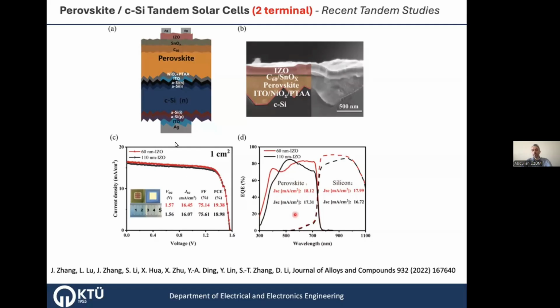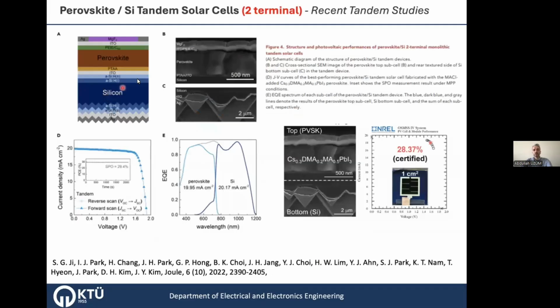Okay, so here's an example again with the silicon heterojunction bottom device. They make the surface flat and they introduce a recombination junction with the ITO again and build the perovskite solar cell on it. You can see in some structures a magnesium fluoride front surface or lithium fluoride. This usually acts as an anti-reflection coating, the same phenomenon as I explained before. And here are the EQE, quantum efficiency graphs, for the front perovskite top cell and the rear side of the bottom cell. They reached more than 29%, but the certified efficiency is around 28%, which is also a recent study.